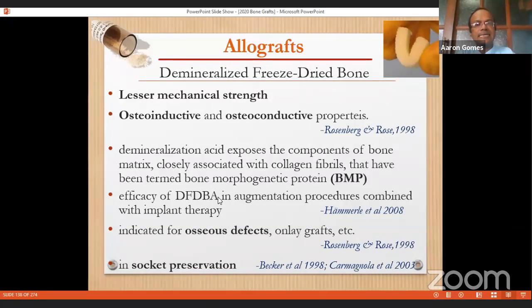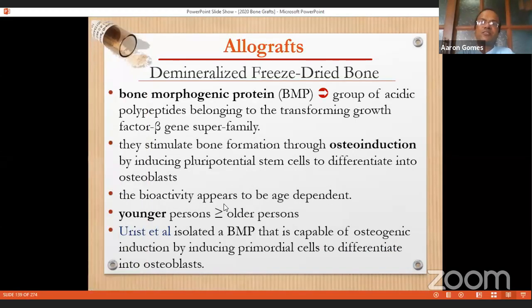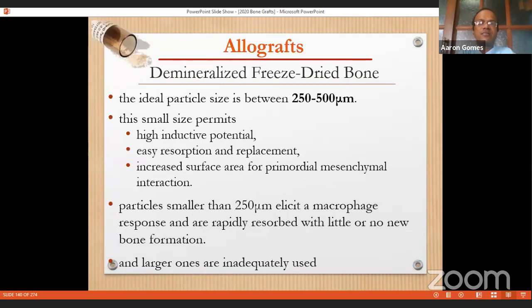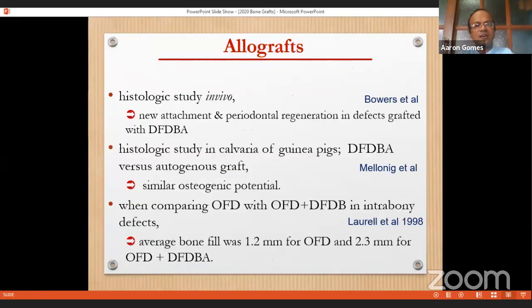They are indicated for osseous defects, implant sites, and socket preservation procedures, and they stimulate bone formation due to osteoinduction. However, you must note that younger donors will have a greater amount of bone morphogenetic protein than older donors. So the ideal particle size is around 250 to 500 microns. This size permits a high inductive potential because if you had a smaller size, they would have resorbed much faster, and with a bigger size, they would have a problem during integration. So the larger ones will not be well integrated, and a smaller size will elicit a macrophage response and faster resorption. So this size becomes ideal for expressing the bone morphogenetic proteins and the osteoinductive potential of the DFDBA.